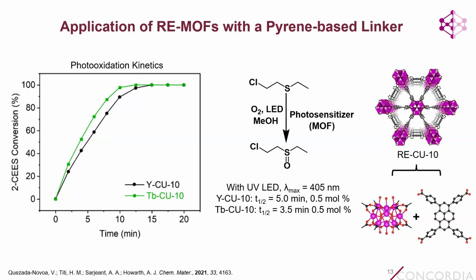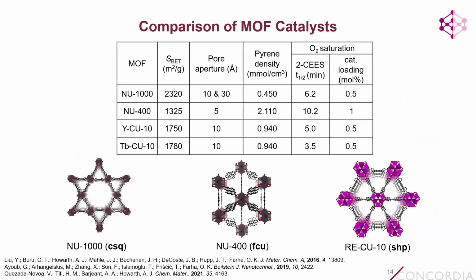And what we see here is the conversion versus time profile for both of these MOFs. So in both cases, the reaction goes to 100% completion. It is selective for the sulfoxide, so we don't see any presence of the sulfone. And when using only 0.5 mole% of each of these MOFs as catalysts and irradiating with UV light, we see half-lives for these detoxification reactions of 5 and 3.5 minutes for the yttrium and terbium analogs, respectively. And so these are actually some of the fastest half-lives that have been reported in the literature for this reaction to date. And so what we want to do is we want to understand why Cu10 is such a great